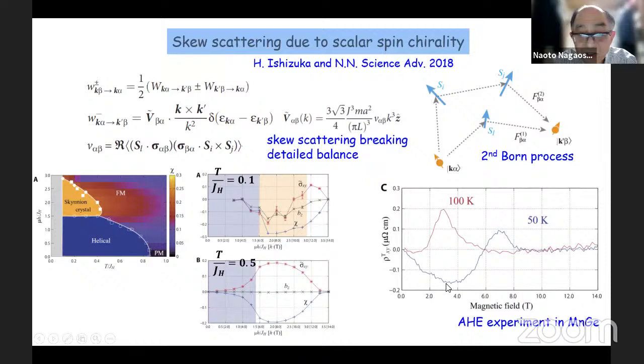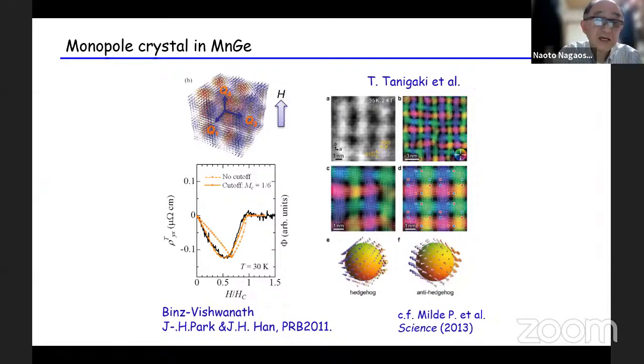So this corresponds to this experiment data of 50 Kelvin. But for higher temperature, we have a single peak. So there is a good correspondence between this numerical calculation and the experimental observation in the crystal of manganese germanide. So this scalar spin chirality plays some important role in this rather conventional chiral magnets. But we can go further.